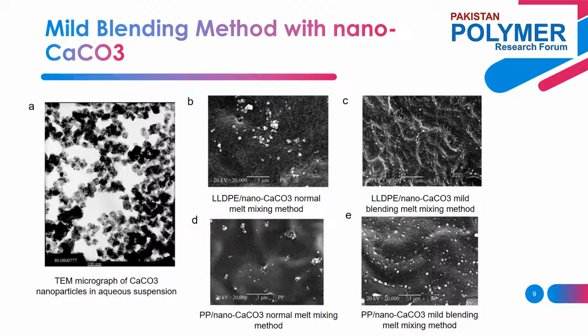Transmission electron microscopy analysis of the nano calcium carbonate suspension confirmed the presence of primary size dispersion of nanoparticles in the aqueous medium. The clear border of the primary particles indicated that the particles were cubic, and the diameter varied from 30 nanometers to 80 nanometers. The dispersion of nano calcium carbonate particles in the matrix was assessed by SEM, as shown in figures B, C, D and E. Figures B and D show the SEM photographs of nanocomposites of LLDPE and nano calcium carbonate, and PP and nano calcium carbonate, formed with the normal melt mixing method.